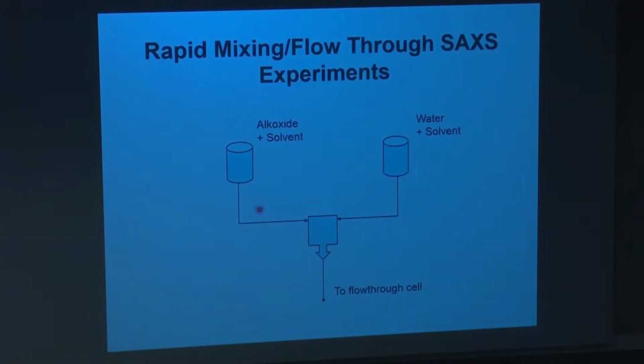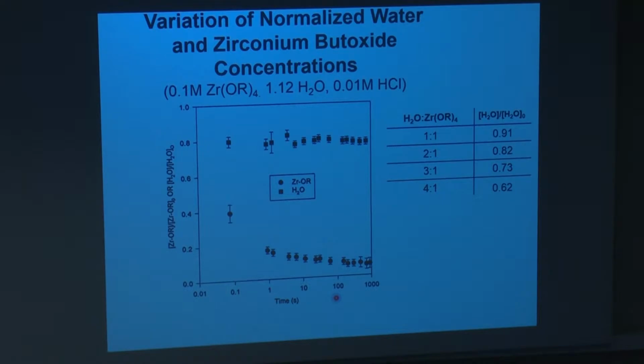So this is a simple technique that I use where we have a solution of alkoxide and solvent, and water and solvent. Also sometimes we put an acid in this system over here and mix these two in a mixing tee and then allow it to flow, and either do the FTIR measurement or the small angle X-ray scattering measurement some distance away from the mixing tee. And with that, you can get kinetic information. So these are the data that we're able to get.